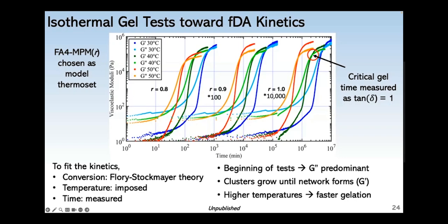In rheometry, the only practical measure of conversion that's available is what is predicted at gelation. So say Flory-Stockmayer theory. And in these tests, the temperature I've imposed, and then I'm measuring the time till gelation. And so that's how I went about the forward analysis. And as you can see in these tests, the loss character starts off mainly viscous at the beginning, since it's just a raw resin. And then once enough clusters and a network forms, the elastic character eventually overtakes the viscous character. And these are still temperatures where the forward reactions are predominant. So naturally, a higher temperature leads to faster gelation.